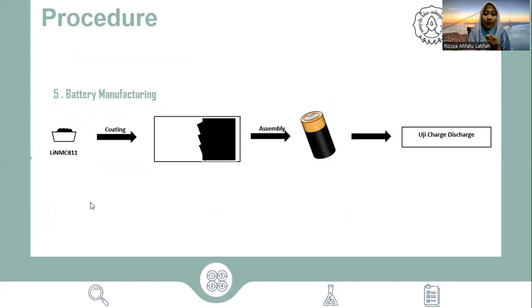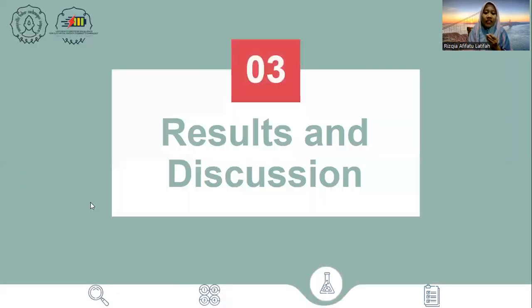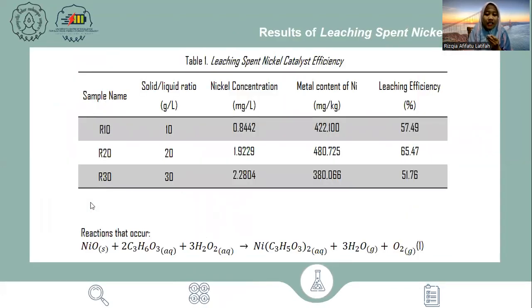The lithium nickel manganese cobalt was coated, and then the cathode is made, the battery is assembled and characterized. Next, the results and discussion. The leaching efficiency is shown in Table 1. Efficiency increased at the variation of 20 g/L and decreased at the variation of 30 g/L. This happens because the solution is already at the saturation point. The highest efficiency was obtained from the variation of 20 g/L, which was 65.47%.